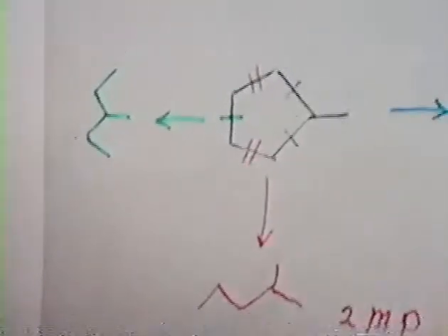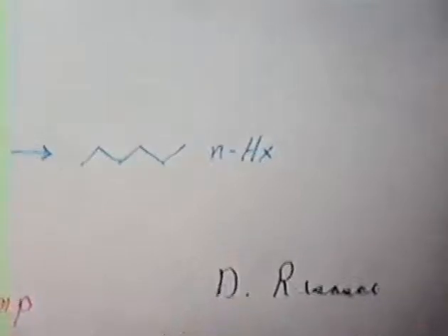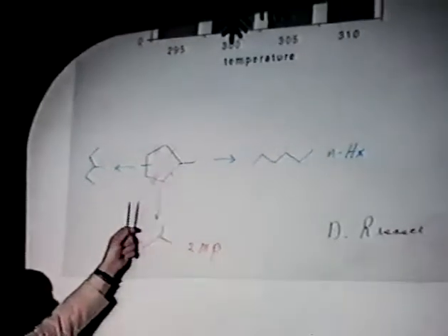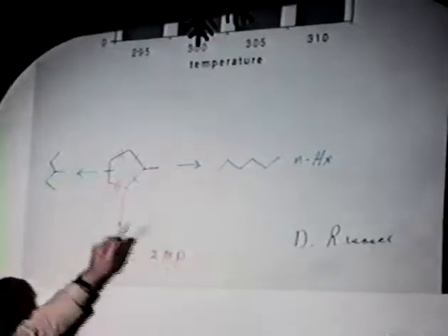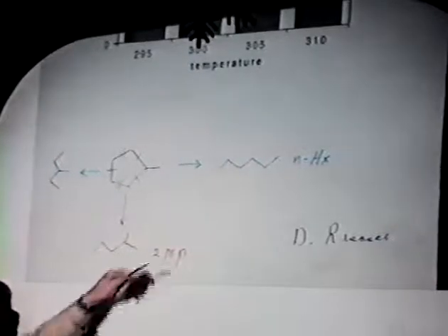The idea was that you choose a molecule where the conformation ought to be pretty well defined, i.e. methylcyclopentane, and now look at the selectivity between the possible hydrogenolysis products. It can crack here or here and go to hexane, or here and go to 3-methylpentane, or here or here and go to 2-methylpentane.